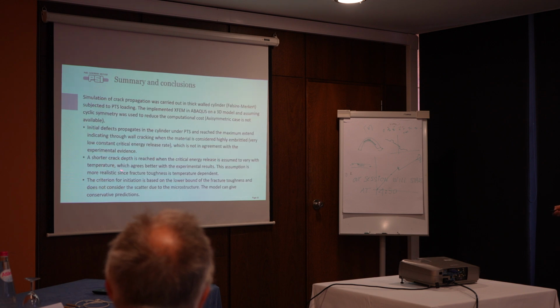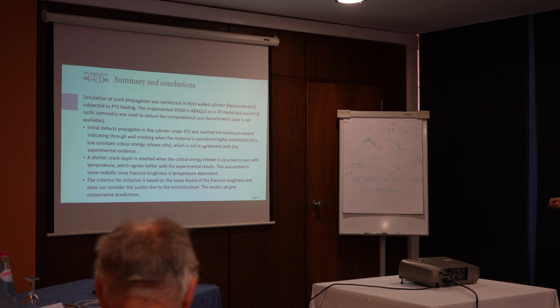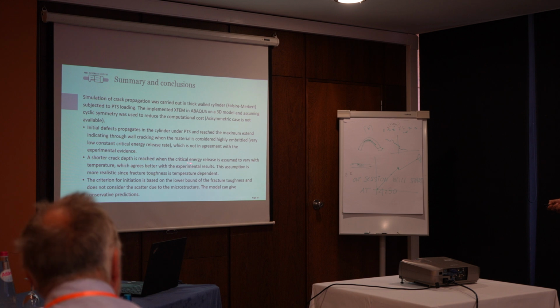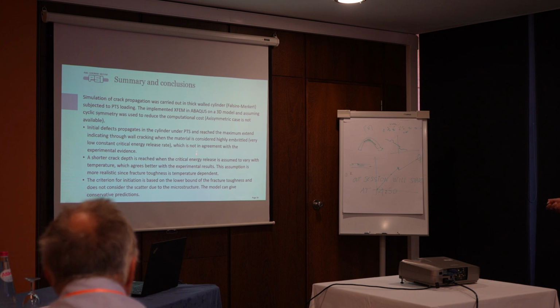So in summary, we simulate the crack propagation on a thick-wall cylinder subjected to PTS. We use XFEM as it is implemented, no changes there. And we assume an axisymmetric case because of the explained reason. So the defect practically closes the specimen when we consider constant energy release rate, and we can control the growth of the crack when we consider temperature-dependent properties.